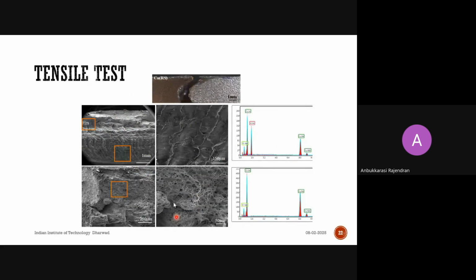Again, the same sample, yes. From here only we could come up with that fatigue test. During the tensile test we could see the top layer fractured along the copper, and the bottom layer fractured along the interface. So how can I ensure that it failed along the interface, and how it failed along the copper? This is the fractured region. As it is, we took it to the SEM. This is the cross section of this fractured face.